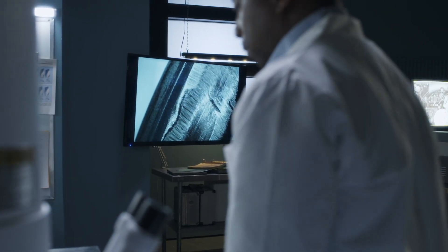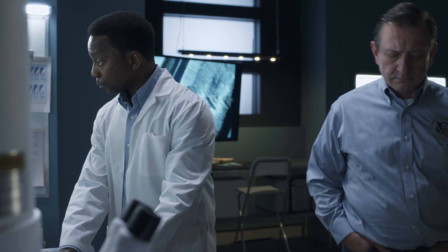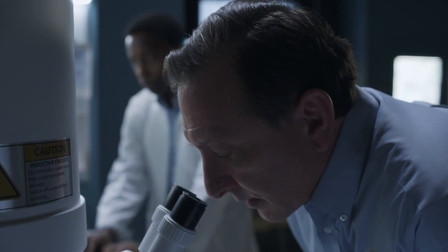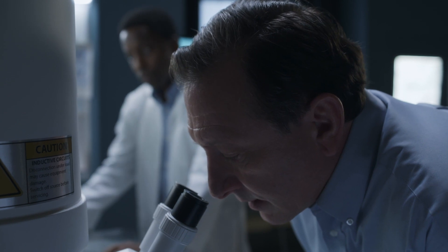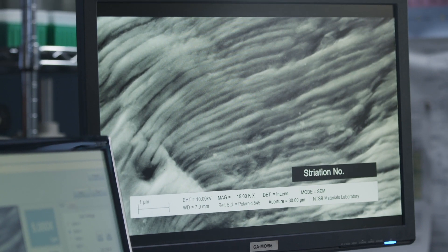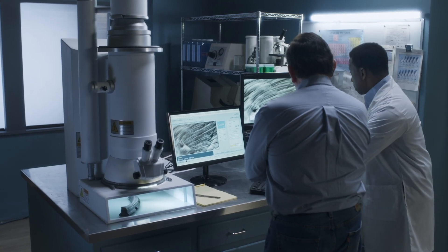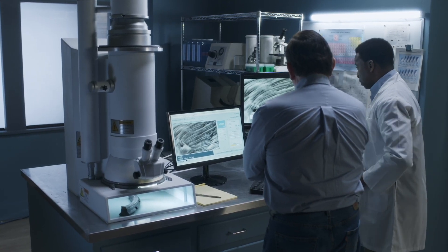A microscopic examination of the fracture surface might tell them more about when the metal fatigue started. The crack was growing. Using high magnifications, investigators can see tiny tracings called striations. There's thousands of them.